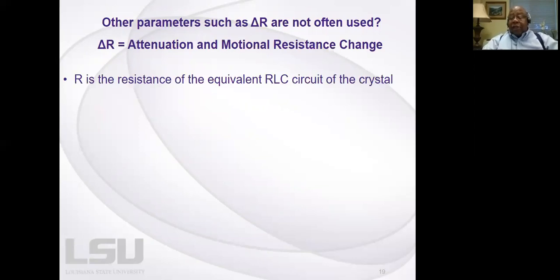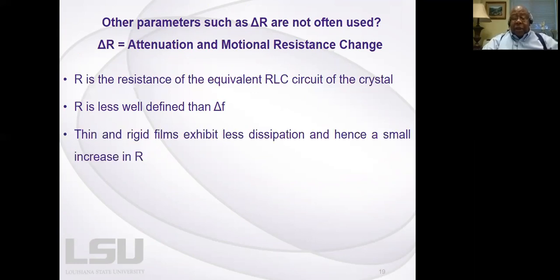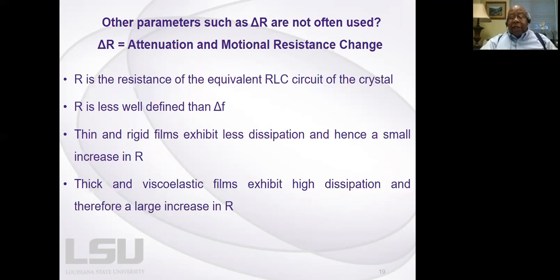R is the resistance of the equivalent RLC circuit for the crystal and how that crystal vibrates. R is less well-defined than delta F. There's no exact equation as you have with the Sauerbrey equation. Thin and rigid films, what they've observed, exhibit less dissipation and hence a small increase in R, whereas thick and viscoelastic films exhibit high dissipation and therefore a large increase in R.